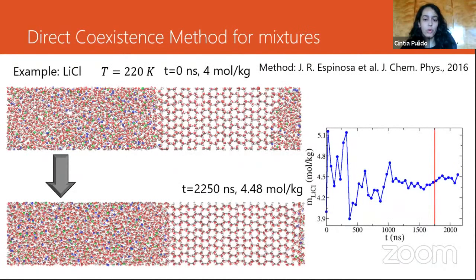But what happens when we have mixtures, like in the example for lithium chloride, where we also have a certain concentration of the fluid. Here we simulated at a temperature of 220 Kelvin, which is below the temperature of coexistence for that molality of the solution. So what happens is that the ice will grow, but at some point it stops. We reach equilibrium. Why? Because when part of the water has solidified, we have fewer molecules of water for the same molecules of salt, which raises the concentration. And now at this concentration, the temperature of the simulation is the one of equilibrium, the melting point. And as we see, for mixtures we only need one simulation. We do not need several, like for pure systems.